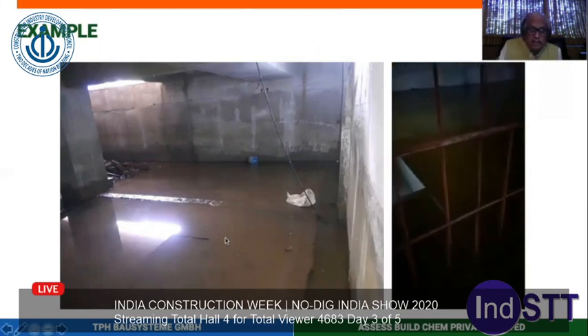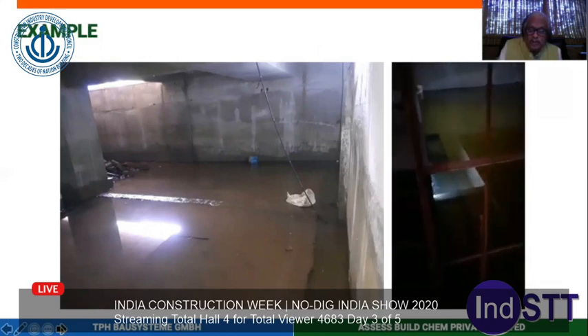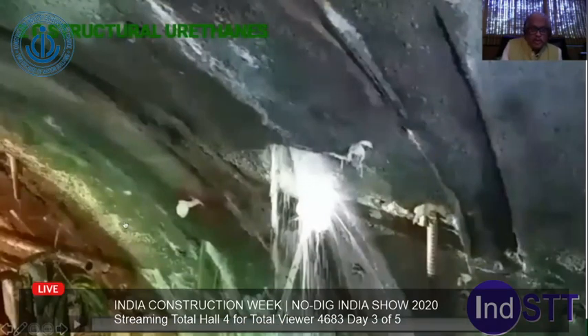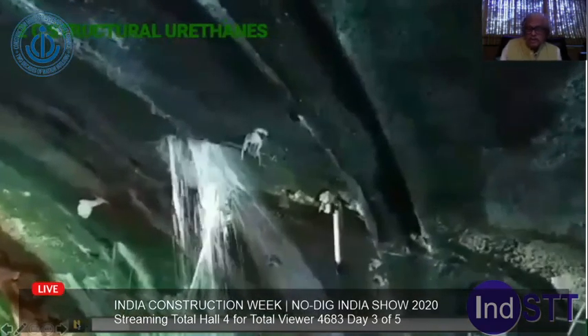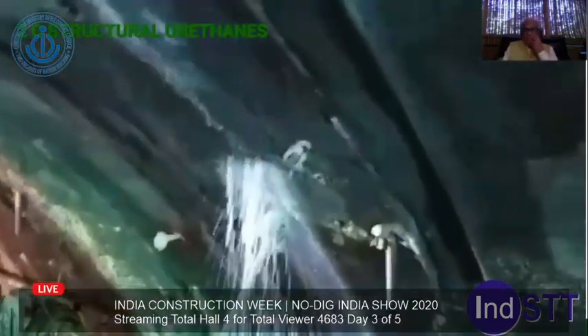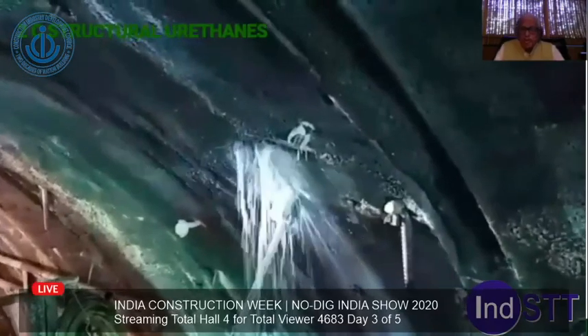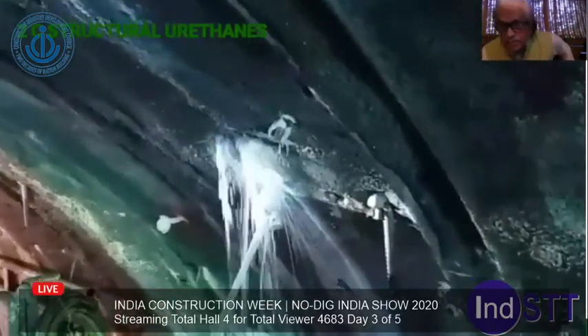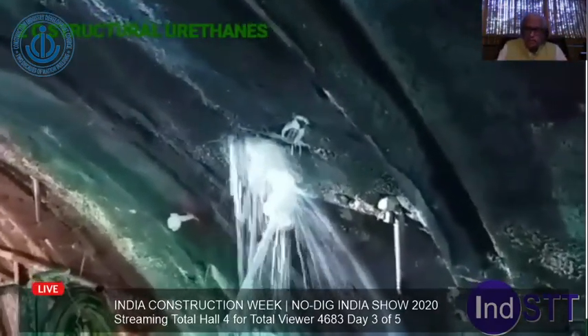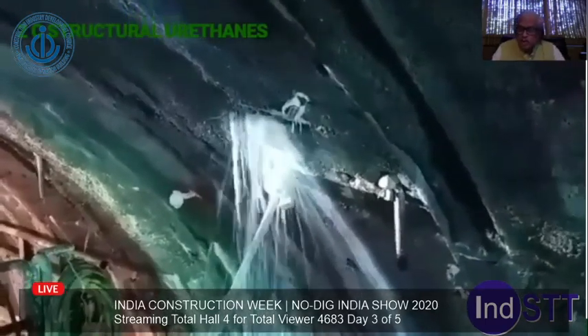Foam is not stable. Foam does not have a capacity to bond to your concrete. Foam does not have the water pressure bearing capacity. So these different polyurethanes are very, very handy when you try to stop water during construction. For example, this is the type of water. You can try to put any foam inside, which expands 50 times or 40 times. It cannot stop the water.